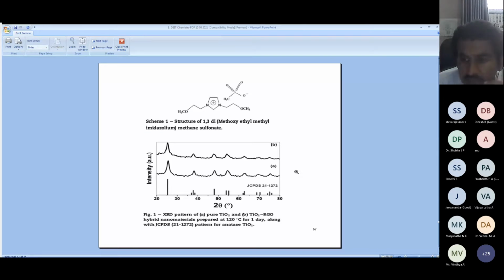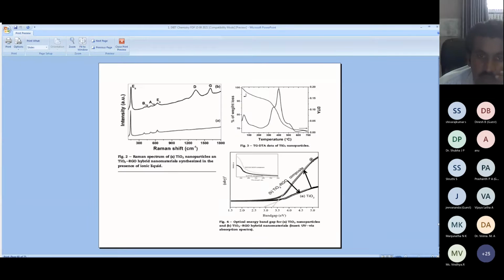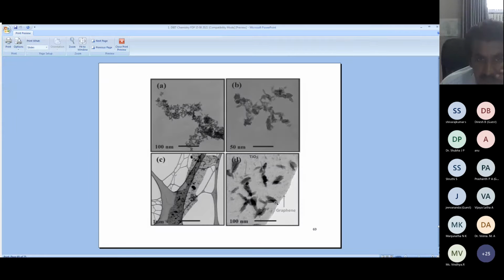We have prepared TiO2 and then TiO2 RGO materials, and the XRD pattern matches with TiO2. We have mentioned the peaks at 21, 1, 2, 7, 2, and this Raman shows the presence of the TiO2 RGO composite. Again, we did the band gap, and TiO2 RGO shows a smaller band gap when compared to the pure TiO2 material, so it shows good photocatalytic activity.